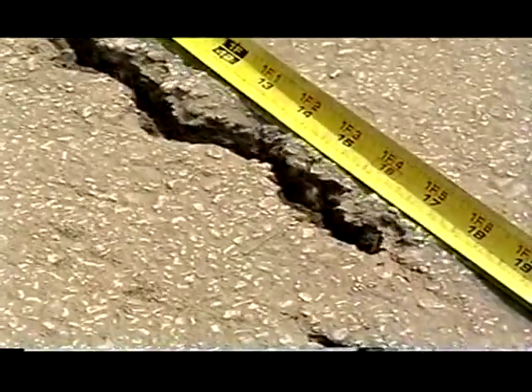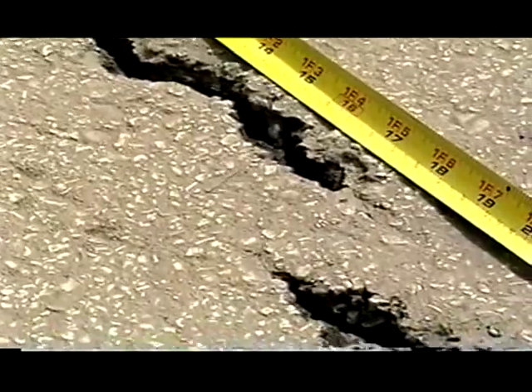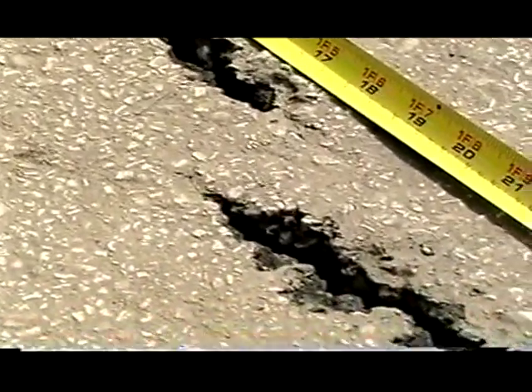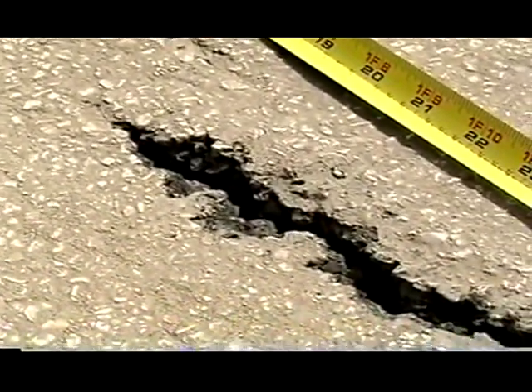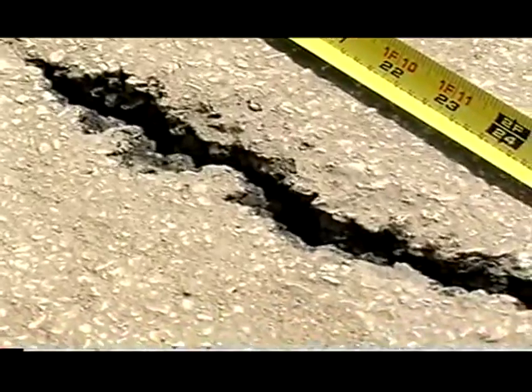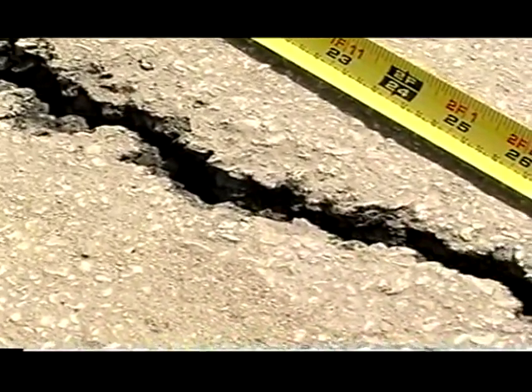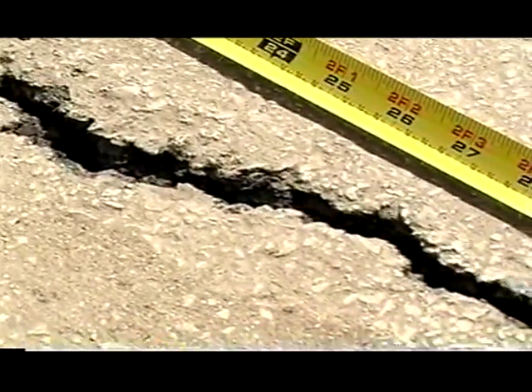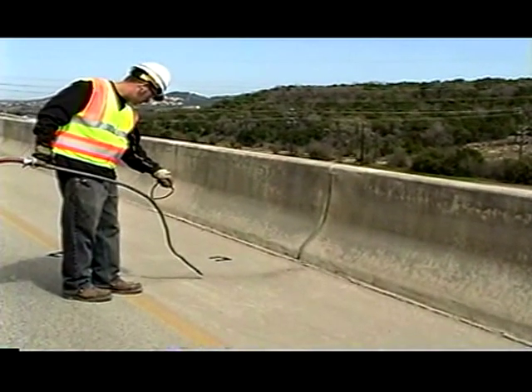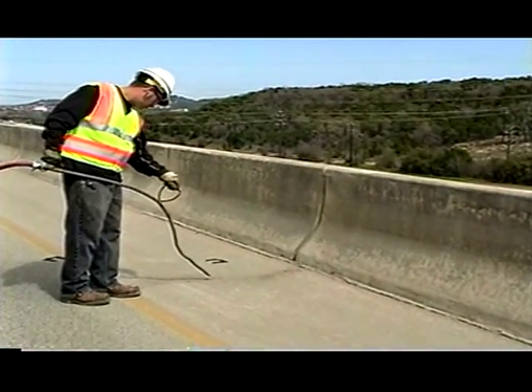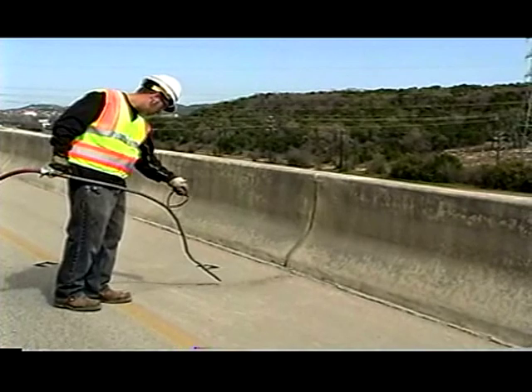Whether the crack has been routed or not, it should be thoroughly cleaned to ensure a clean, dry channel and to optimize adhesion of the sealant to the crack surface. This is one of the most important procedures in crack treatment, since most recorded failures are due to loss of adhesion. High-pressure air blasting is the most common technique used in crack cleaning.